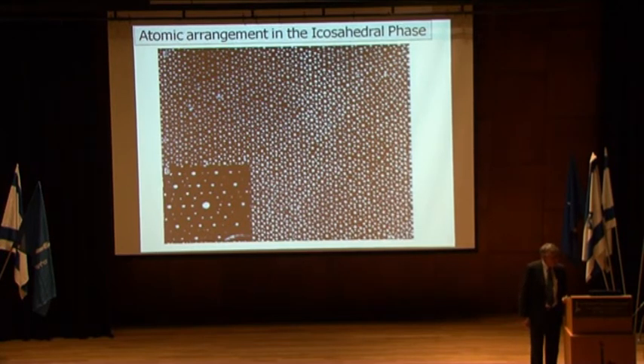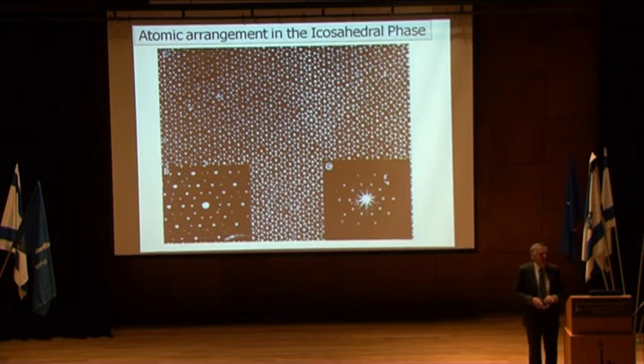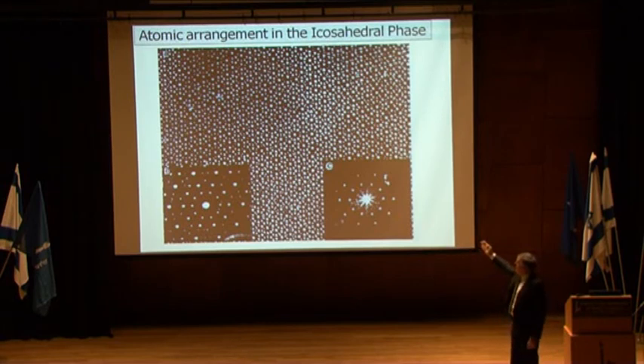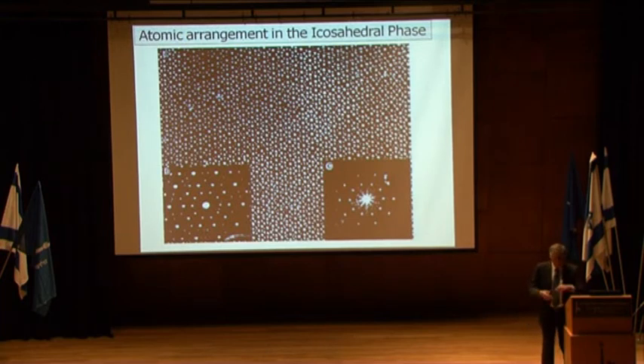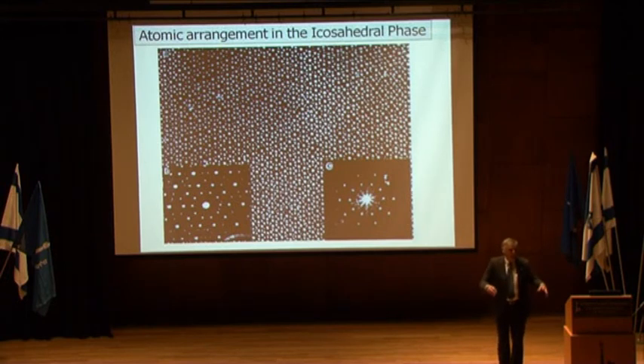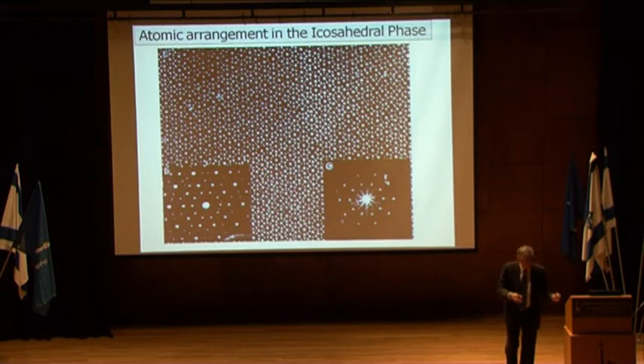Now, what my friends did, they also took an optical diffraction pattern. An optical diffraction pattern is a pattern. You take the picture of the lattice image, you put it on a slide. Nowadays, you can do it on the computer within 2 seconds. But at that time, we put it on a slide, make it very, very small, and shine a laser beam through the slide. And what you'll get is an optical diffraction. And that optical diffraction looks like the one on the right. So this is an electron diffraction, this is optical diffraction. So you can say, okay, big deal. Both are Fourier transforms of the image, 2 different ways. That is true. But let me show you what experiment you can do.